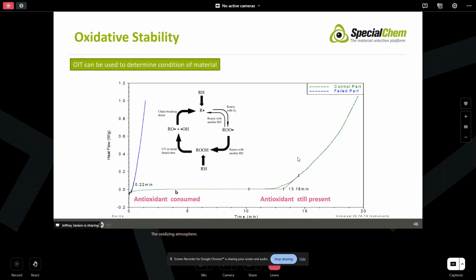So here's an example. Here's our two parts that came out of the field. One in a mild environment, and this is time zero now, as we re-zeroed the curve. This is after the air is turned on, the oxygen is turned on, and we get about 13 minutes before the polymer starts to react. Our failed sample starts to oxidize immediately, and so that tells us again that the antioxidant has been totally consumed, and that this material is not being protected, and it's another way to understand whether the material has been degraded during field service, and by what mechanism.